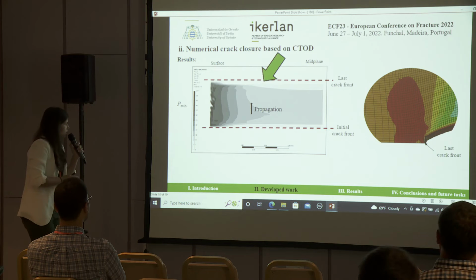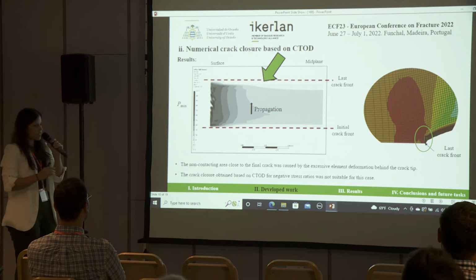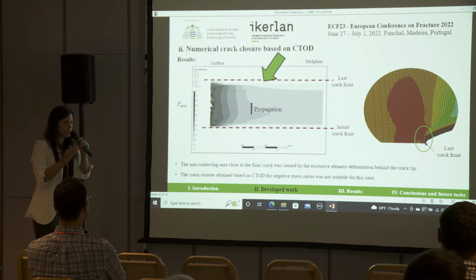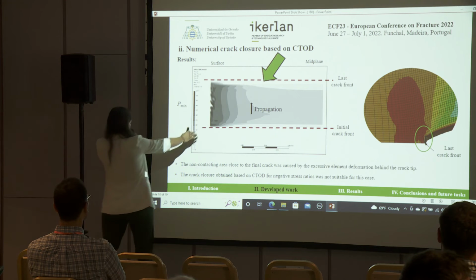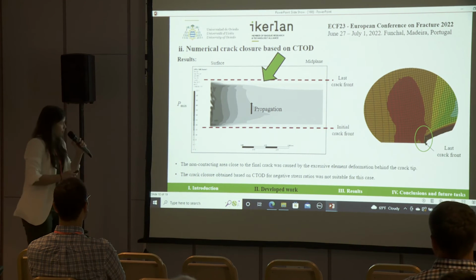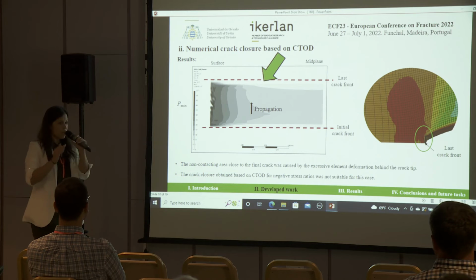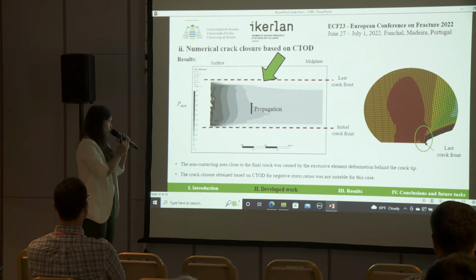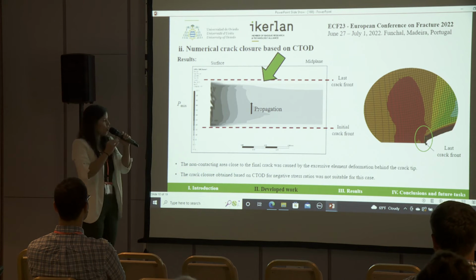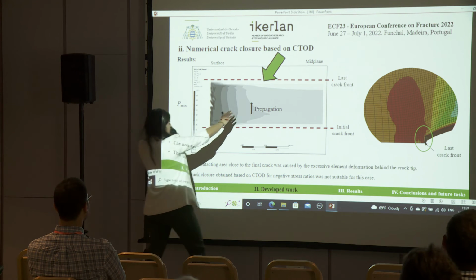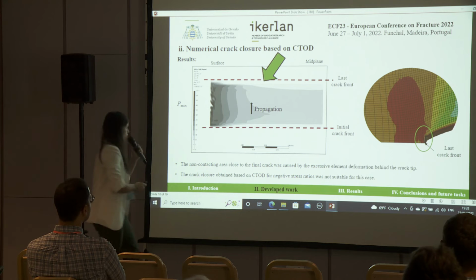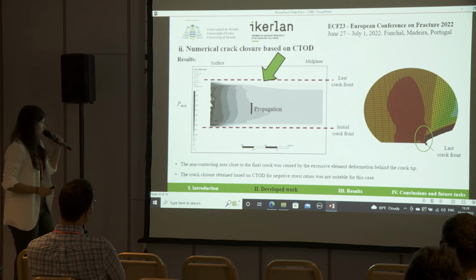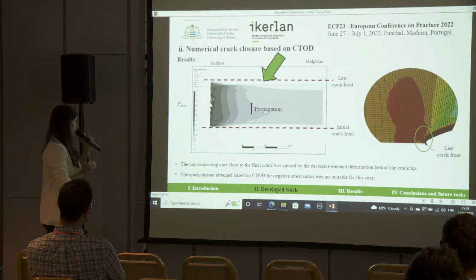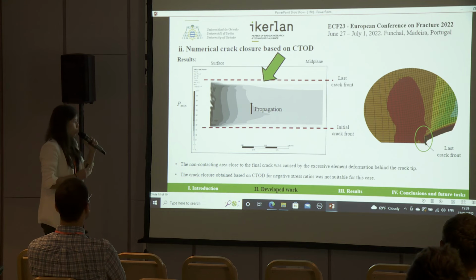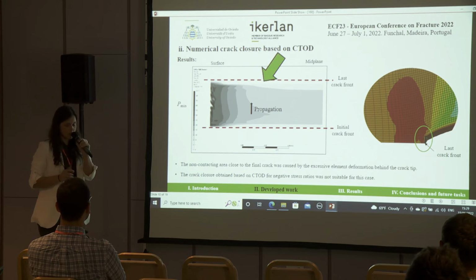Here, you can see the contact element pressures from the beginning to the end of the crack propagation. There was a non-contact area, close to the final crack, that was caused by the excessive element deformation behind the crack tip here. So it can be stated that the crack closure obtained based on the CTOD for negative stress ratios was not suitable for this case.